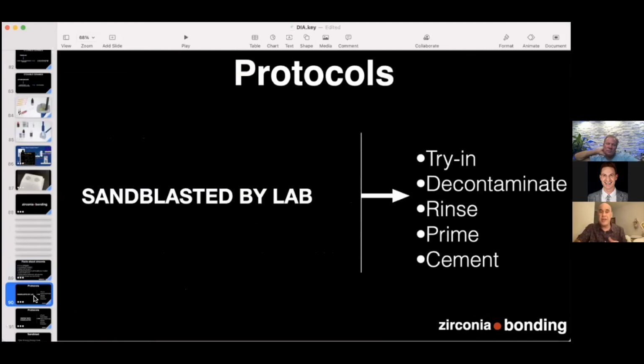So what are the protocols? Here's my first one. If your lab sandblasts the zirconia for you, you try it in as soon as you get it. Well, as soon as the patient sits, you try it in. As soon as you try it in, it becomes 100% contaminated by the saliva. You're done. You cannot bond. Now you need to decontaminate that zirconia. And there are ways to do that, and I will show you. Okay. Once you decontaminate and rinse it, you prime it with an MDP-containing primer, and then you do your cementation procedure, whatever that is. It doesn't matter. But you need to clean that zirconia crown.